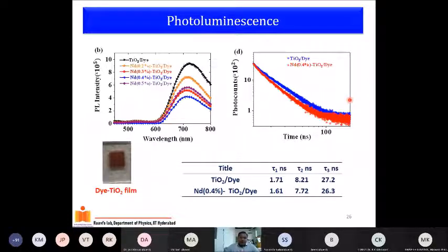One point I should highlight is that when you have the dye and titania, we know that the electrons from the dye are injected into the titania. So when you excite the dye in the absence of titania, it should give emission from all the population that has gone to the excited state coming down. Let's say 100 is the number of electrons that has gone up to an excited state of the dye. Upon photo excitation, all 100 should come down eventually, releasing 100 photons. Giving an example.